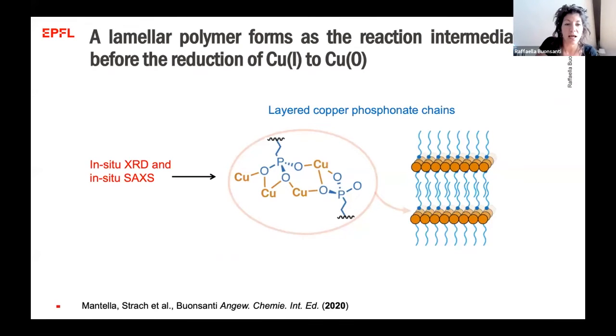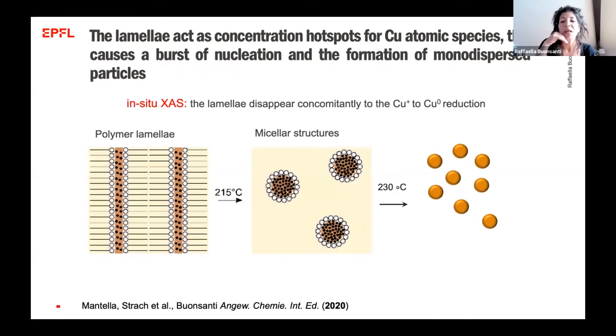Again, to make a long story short, what we found here, using this time in situ X-ray diffraction and in situ small angle X-ray scattering using a similar reaction flask as the one that I showed before, is that actually in this case, the TDPA reacts with the copper to form a layered copper phosphonate chain. So we form a polymer lamella. And then what happens to this polymer lamella is that as soon as the temperature increases, it suddenly transitions to a micellar structure, and then eventually the copper plus gets reduced to copper 0, and we form the particles.